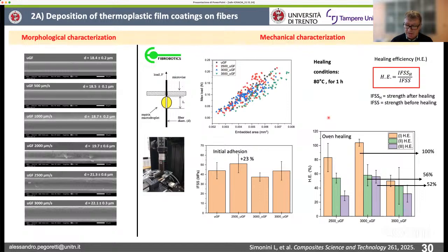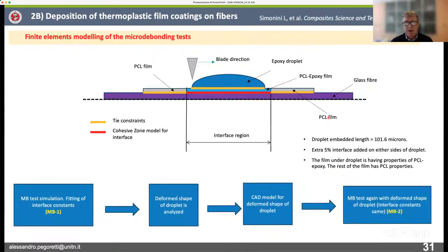And in order to get some insight into the process, we did some modeling by using finite element method. And here you can see how we did model the situation. So here you can see the glass fiber, the PCL coating, the epoxy droplets, and the blade, which are the main actor. And then we analyze basically the process.